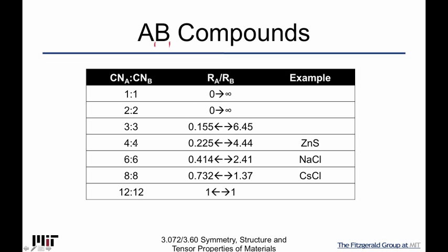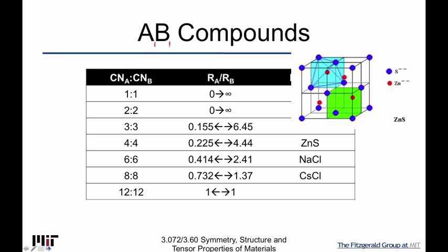It turns out that more covalent materials also have this same kind of setup, but something like zinc sulfide, which is still a very ionic bond, you find out that it forms a zinc blende structure, and the zinc blende structure is essentially just 2 interpenetrating cubic FCC lattices.